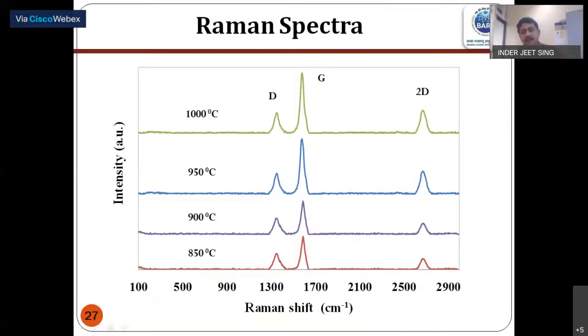It gives a very clear-cut picture about the nature of your CNT. So if it is multi-walled, we get typically 3 peaks: D peak, G peak, and 2D peak. And when it is single-walled, this D peak is almost missing, and we get another peak at the low wave number value, which is called the radial breathing mode peak. That you will see in a subsequent slide.